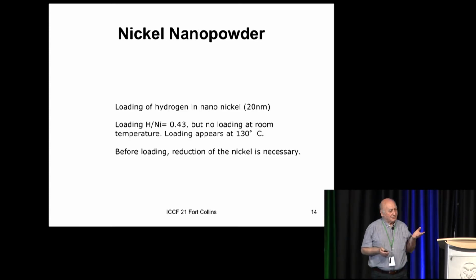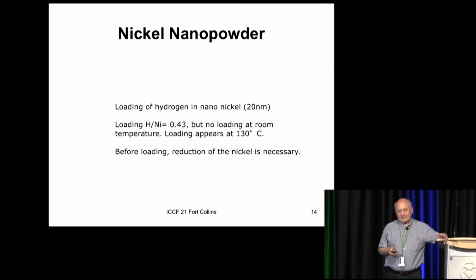Nickel is known not to load, I mean, load at 6,000 atmosphere pressure. And I tried nanopowder of nickel, 20 nanometers. I bought it from a German company. It costs a lot per gram, a lot more than gold. And I realized that if you put hydrogen in nickel nanopowder, it doesn't load. At room temperature, no way.